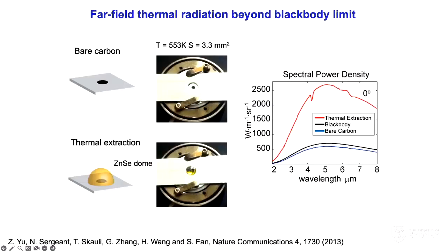So in a conventional thermal radiator, there is an upper bound on how much thermal radiation you can get, and that upper bound depends upon the area of the structure. And it turned out that with photonic engineering, you can also overcome it. This is one of our own experiments carried out by Professor Zongfu Yu, now a professor at the University of Wisconsin. What he showed was that if you take just a black dot of carbon, which behaves as a standard radiator, and you put on top of it a semi-transparent dome, you will actually get a total emitted power that's much larger compared with that black body.